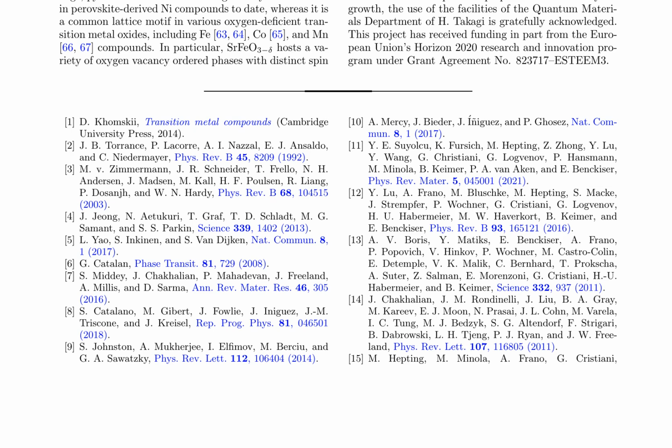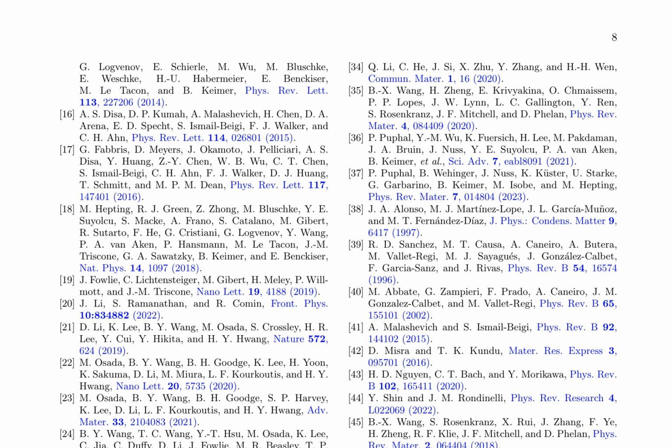They propose that the topotactic reduction of rare earth nickelates and related materials can lead to the realization of phases that might be categorically unattainable by direct synthesis methods. The study highlights the importance of further investigations to accurately determine the reconstructed atomic positions and the crystallographic unit cell, which is likely larger than the 4ap x 4ap x 2ap supercell.